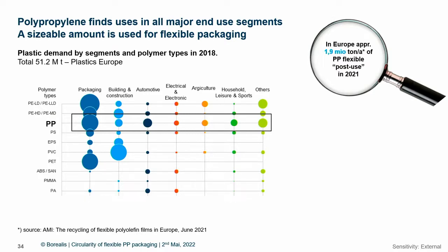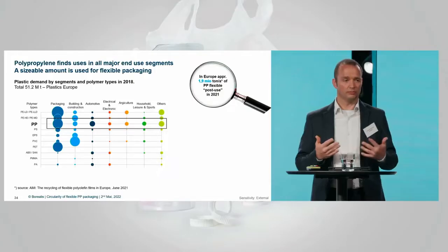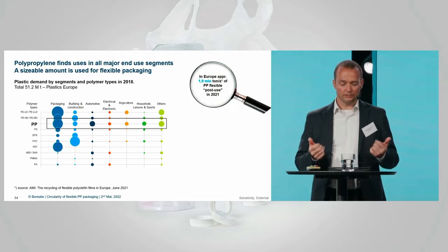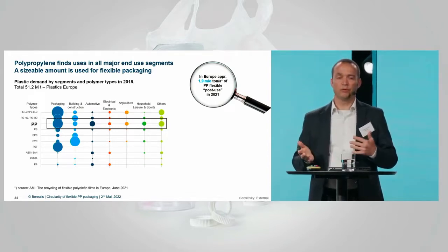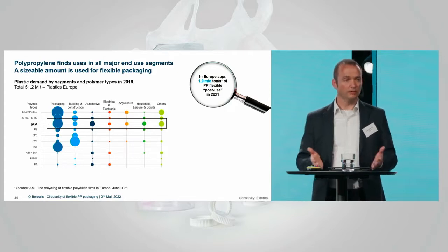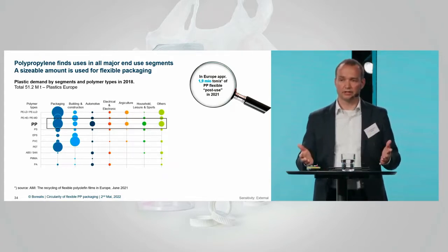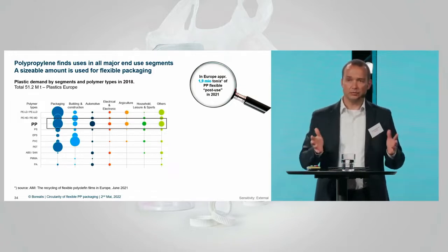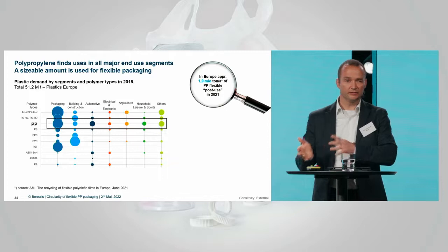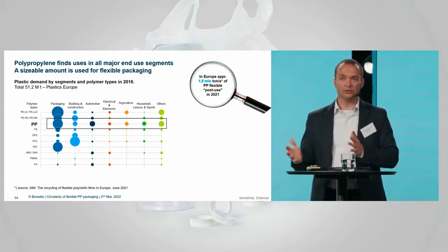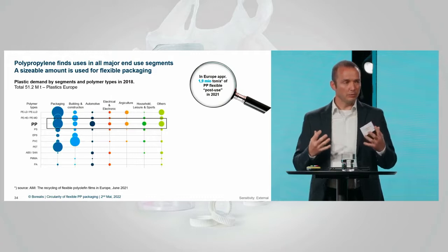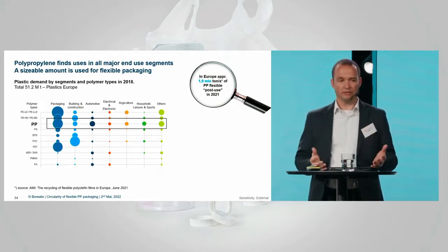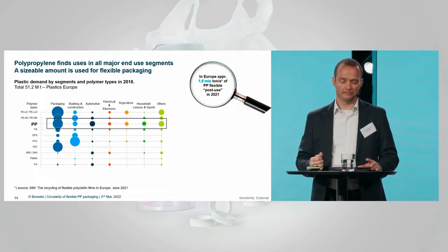So this is really quite a variety of films that you can produce from polypropylene. And that is possible because you can easily tailor-make the viscosity of PP. And finally, also the mechanical and thermal performance of a polypropylene film is extremely versatile. You have a very nice mechanical performance, from soft to very stiff, but also from low melting to very temperature resistant. And that means that with polypropylene you can actually meet a lot of requirements of the flexible packaging industry.